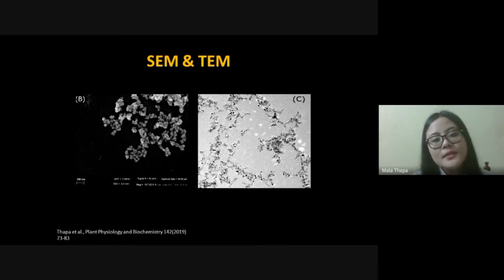These are the scanning electron microscope and transmission electron microscope images of synthesized zinc sulfide nanoparticle, which confirmed that the synthesized nanoparticle were nearly spherical in shape and below 20 nanometer in size.